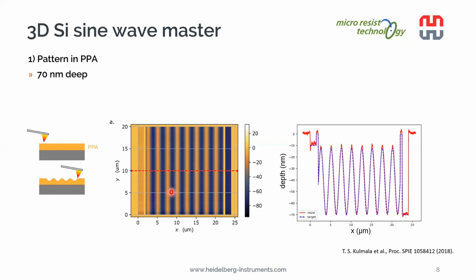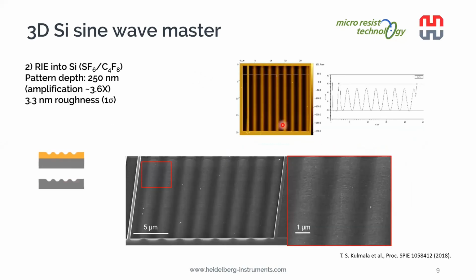Here we have used a sine wave structure as the target pattern. We first wrote it 70 nanometers deep in polymer, and as we can see here on the right, the target depth, the blue, corresponds very well with the actual written depth shown in red. Then we transferred the 3D topography into a silicon substrate using a standard reactive ion etching process, with SF6 and C4F8 gases. As a final product, we get a silicon sine wave 250 nanometers deep, corresponding to an amplification in depth by a factor of 3.6.